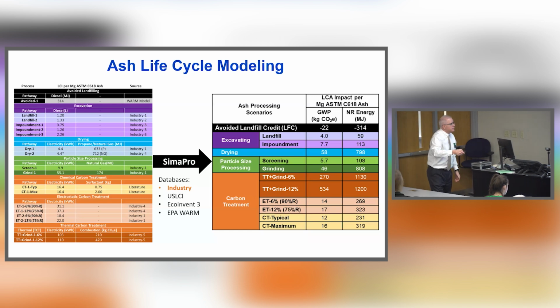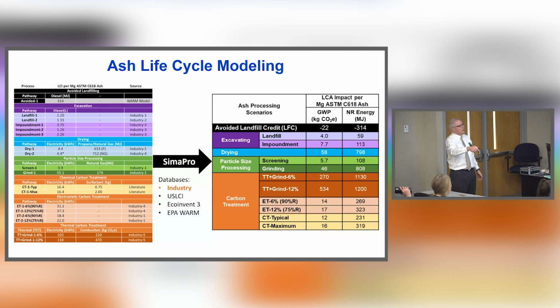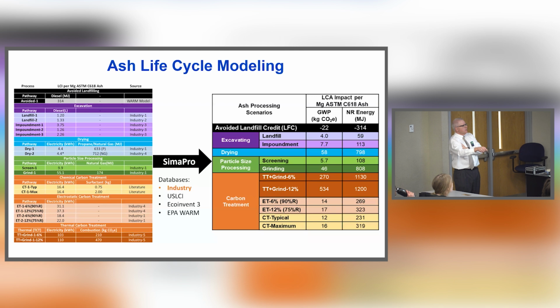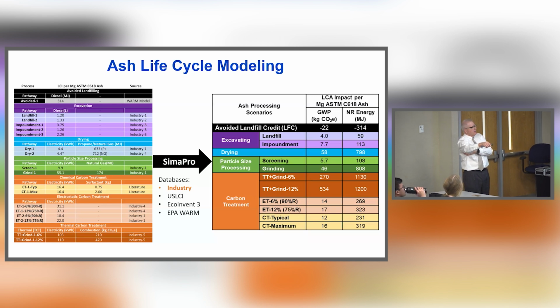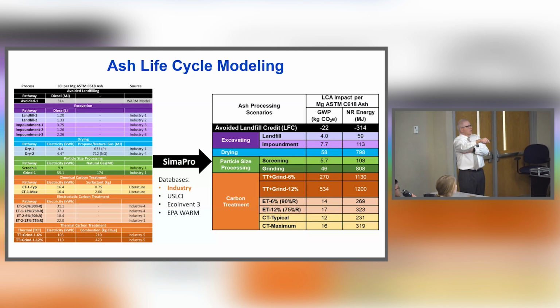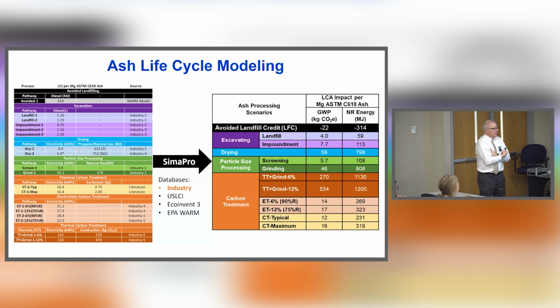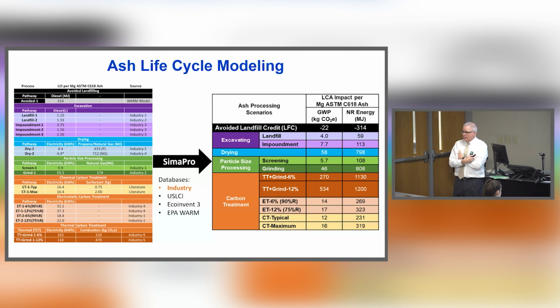And same with the energy. You can see excavating it out of our basin or impoundment uses twice as much energy. The drying process is very energy intensive as well, but you can just look through these different metrics. We went through these for each case, processing, whether screening it, grinding it, and then we looked at different carbon removal techniques. We used so-called thermal treatment.